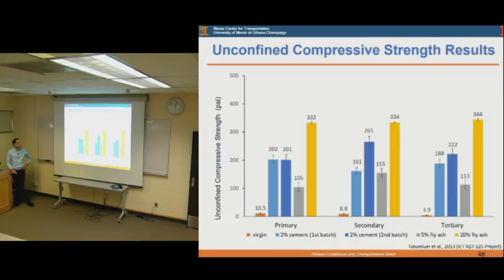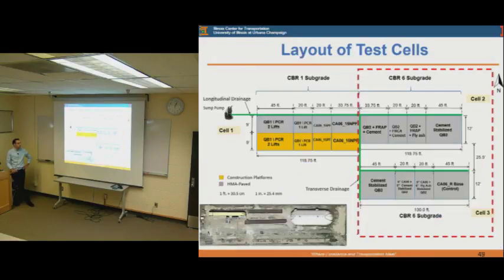And this is basically the test sections that were constructed in cell 2 and cell 3. So the difference is that in cell 1 we had the unbound applications. Now we're talking about the chemically stabilized applications. And we had also proposed 7 different applications of quarry byproducts stabilized with either cement or fly ash, and in some cases blended with another recycled material, such as recycled concrete or RAP, and built on a subgrade 6 material.